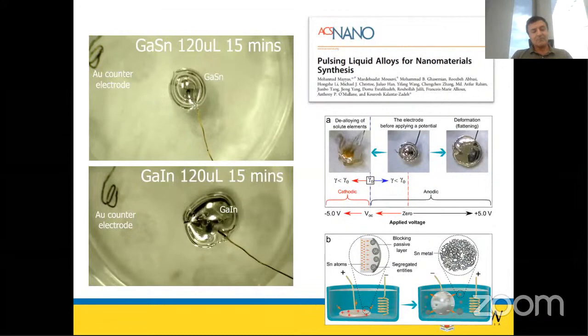Okay, look at one of the examples here. The example is about tin and indium. We basically put tin and indium into gallium, and we know that something is formed if we supersaturate the inside of gallium with one of these elements. The problem is the surface tension of liquid metal is very high. How to take them out? One of the ways of breaking the surface tension is to apply a voltage. Applying a voltage against the surface brings the surface tension to almost zero. Then you apply the reverse voltage, and you can push all these nanomaterials that you create inside the liquid metal to the surface and let them get released into the solution.